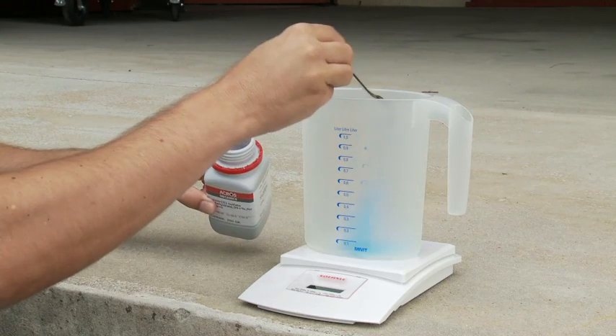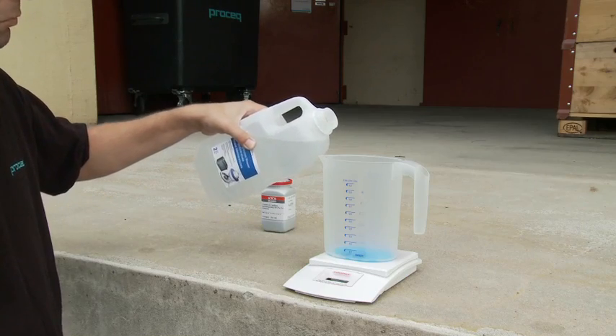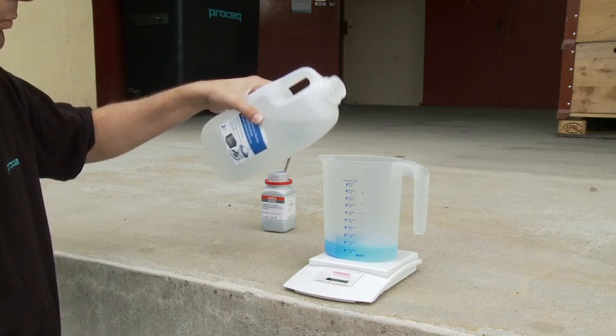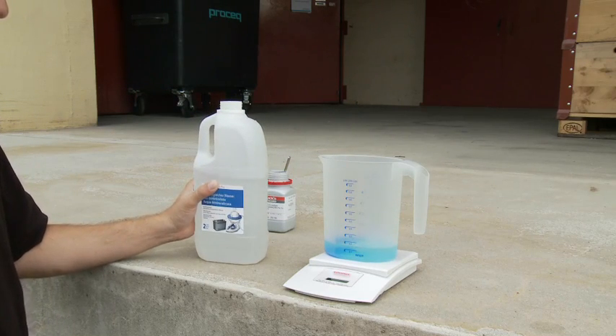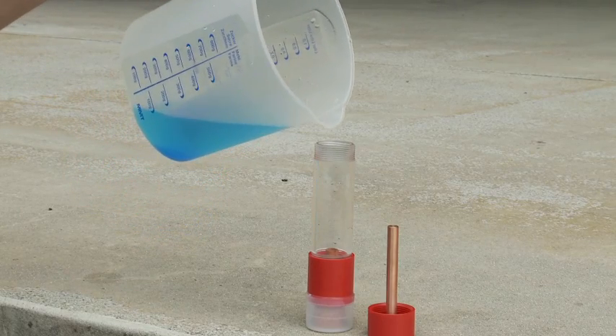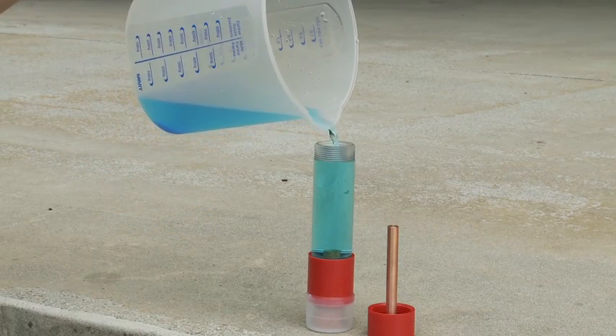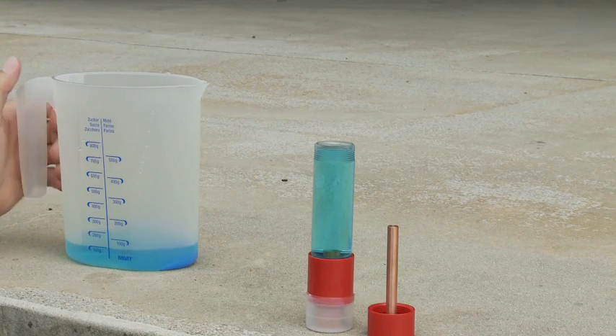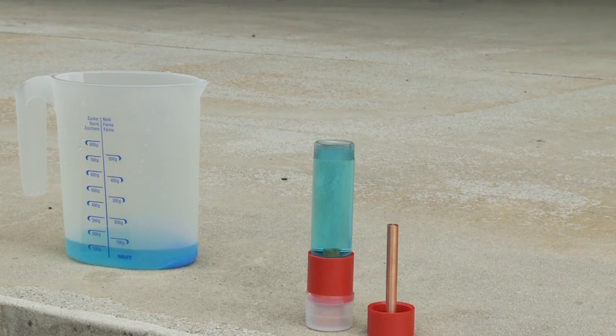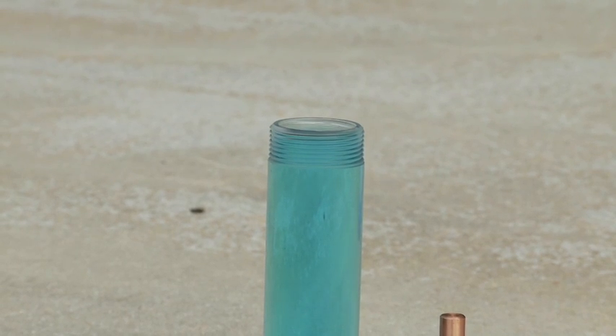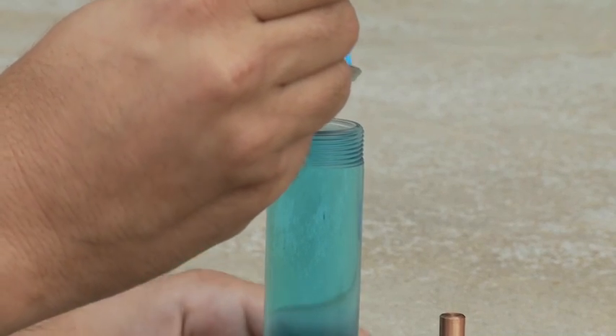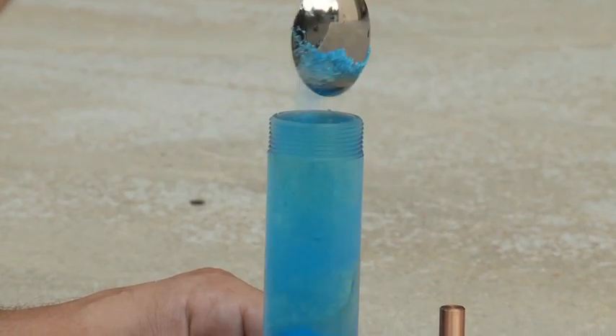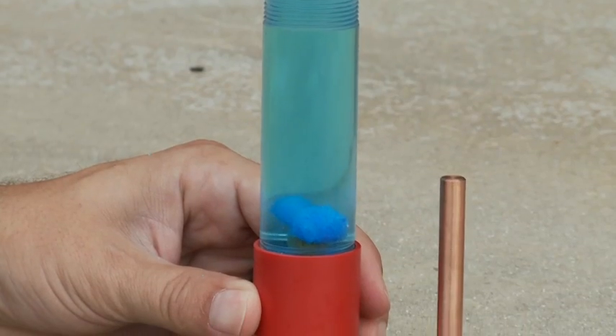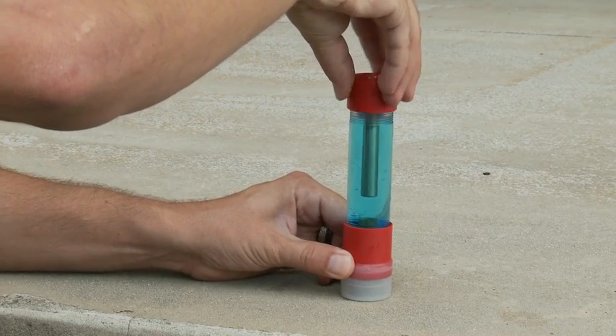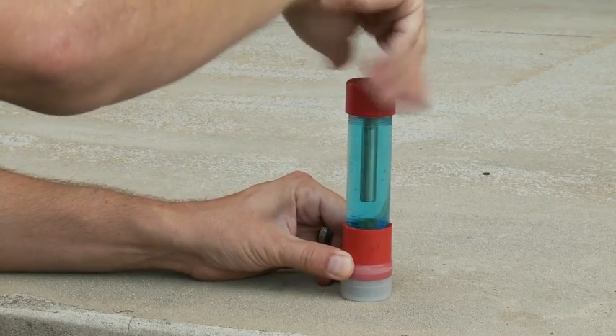Prepare the saturated solution by mixing 40 units by weight of copper sulfate with 100 units by weight of distilled water. The electrode should be filled as completely as possible with a minimum of air in the compartment. This ensures that the solution is in contact with the wooden plug even when measuring in an upwards direction. To guarantee that the solution remains saturated, add an additional teaspoonful of copper sulfate crystals into the electrode. To prevent drying out, close the cap immediately.